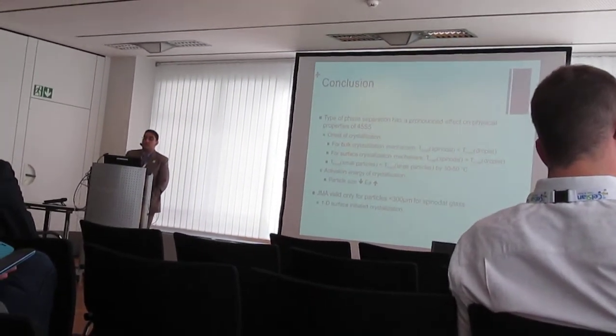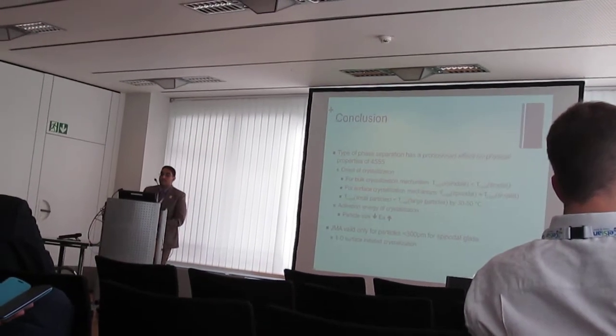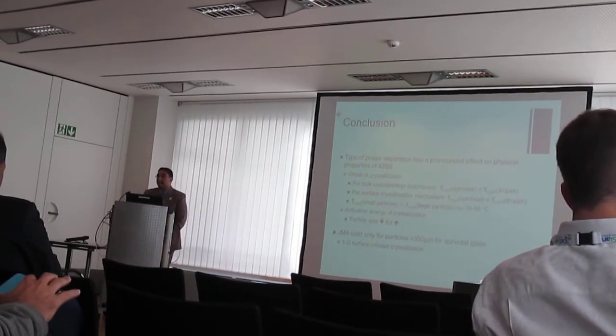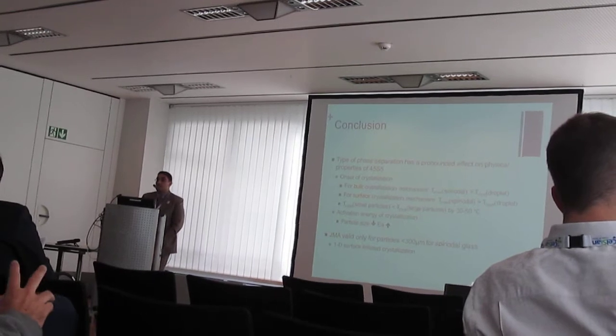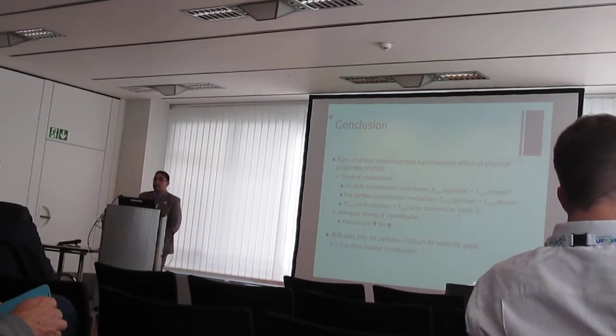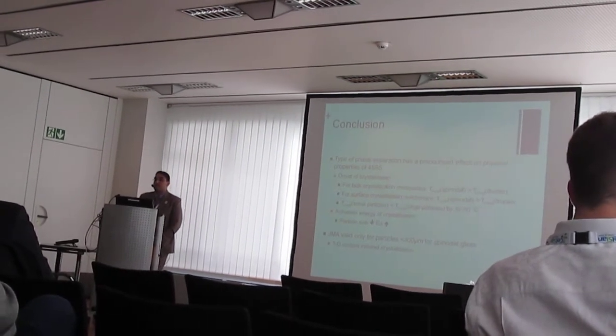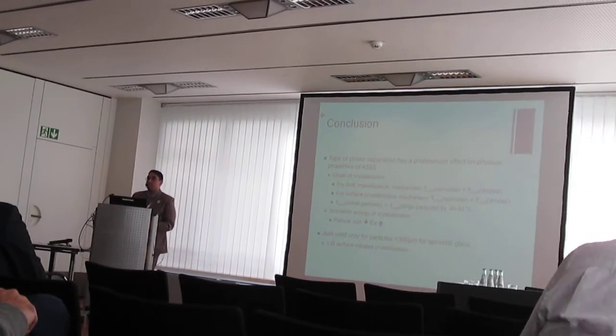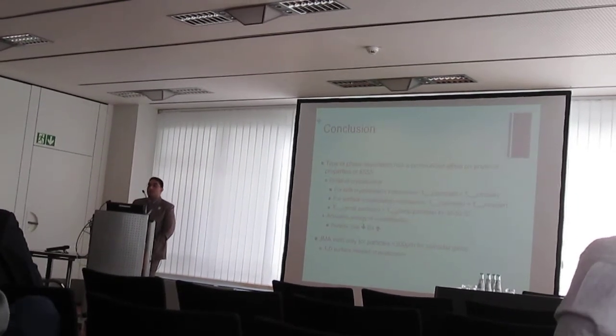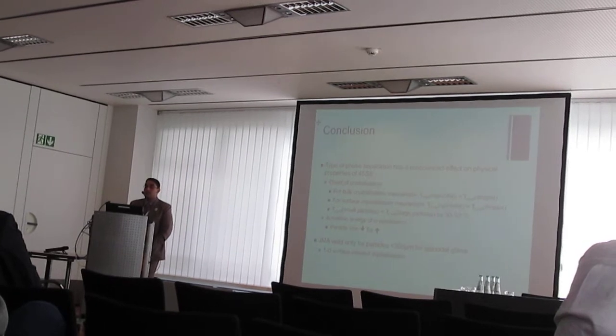In conclusion, the type of phase separation has a pronounced effect on the physical properties of 45S5. As we saw at the onset of crystallization, for bulk crystallization mechanisms, the temperature of crystallization for the spinodal phase separated glass is less than for the droplet phase separated glass. We also saw that for the surface crystallization mechanisms, the temperature of crystallization for the spinodal phase separated glass is about the same as for the droplet phase separated glass, which was seen in the DSC data. Finally, we saw that the temperature of crystallization for the smaller particle size is less than for the larger particle size by about 30 to 50 degrees Celsius.